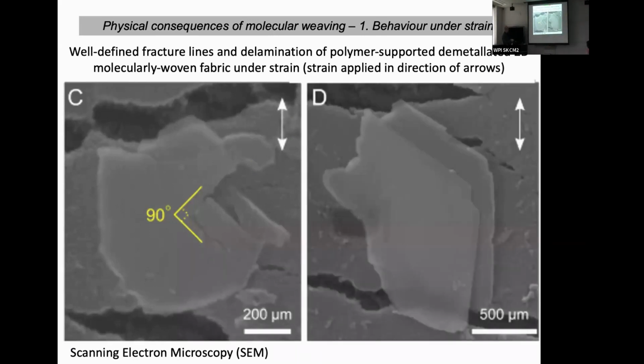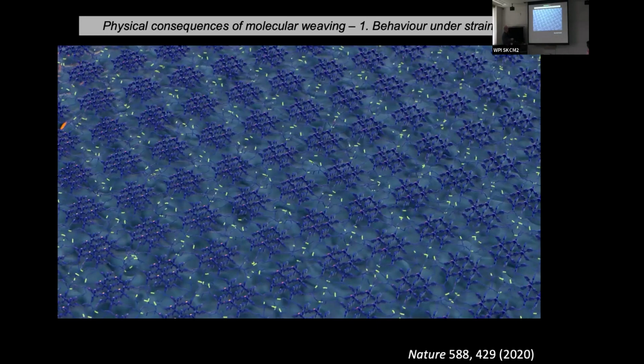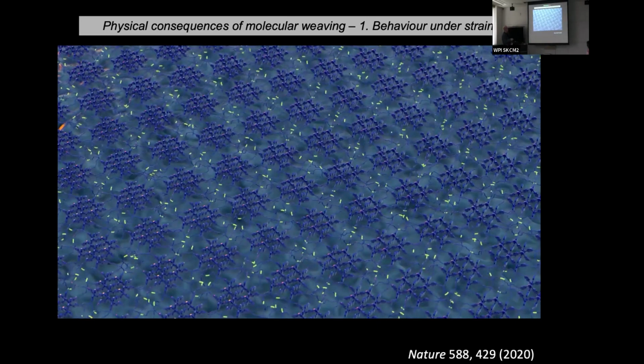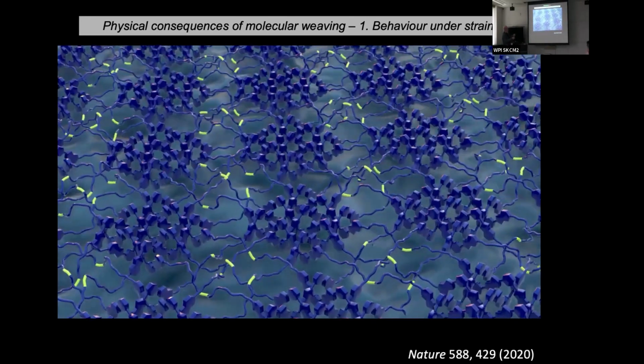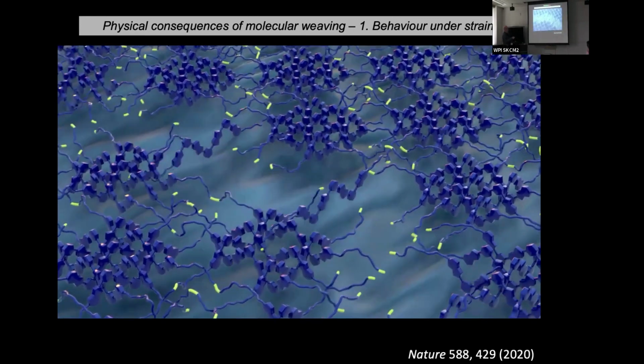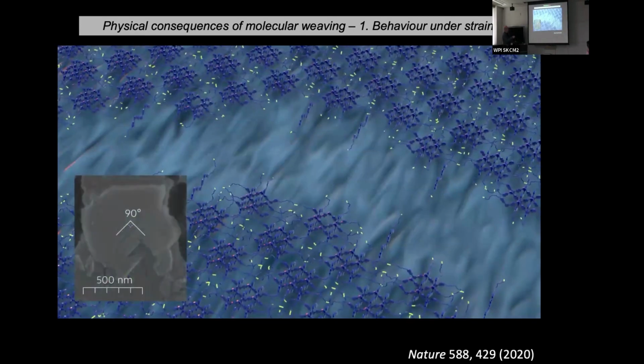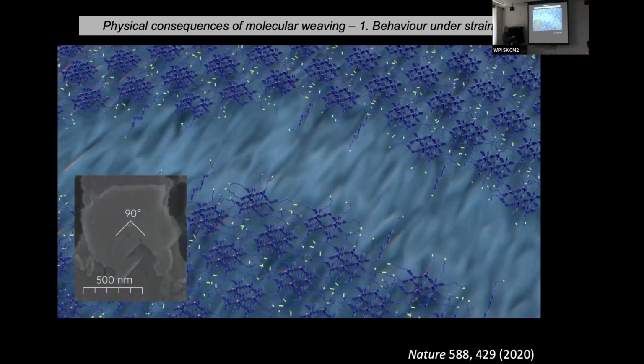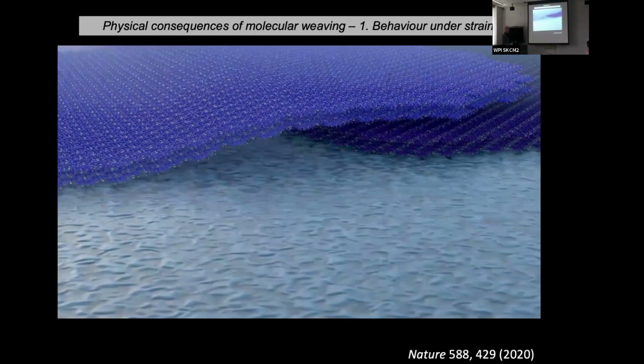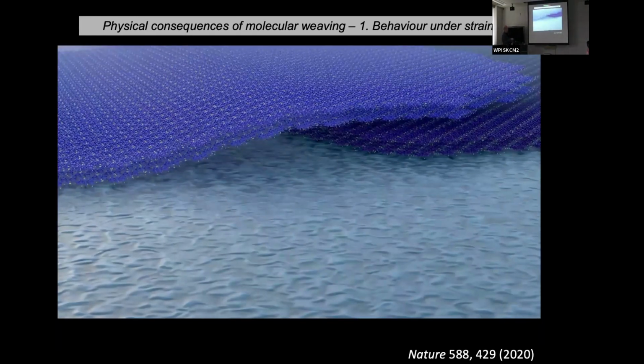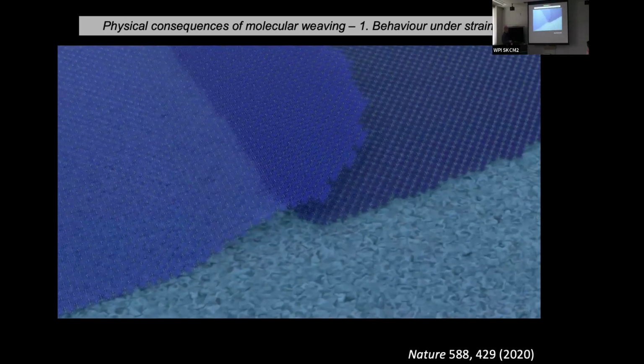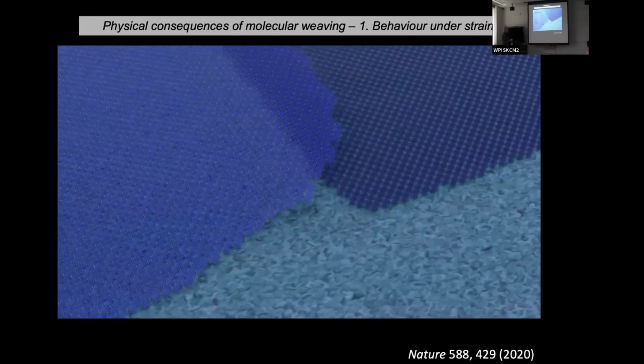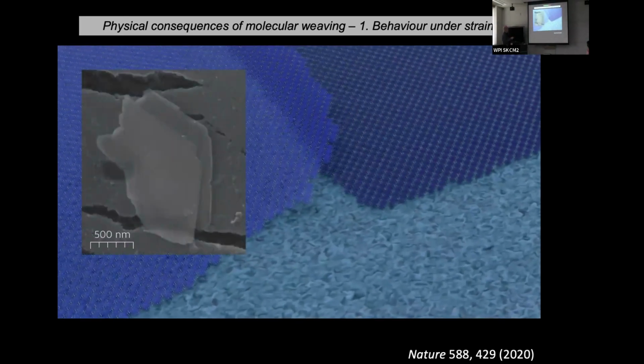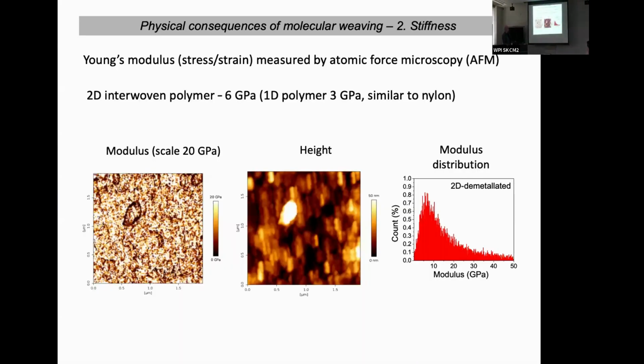It delaminates, again, just like a normal carpet, when you put force on it. So if you put this material on a polymeric sheet, on a plastic sheet, and pull the sheet, it distorts with cracks at these 90-degree angles. And if you have layers of the sheets and you pull them apart, they just delaminate, again, like we see here.